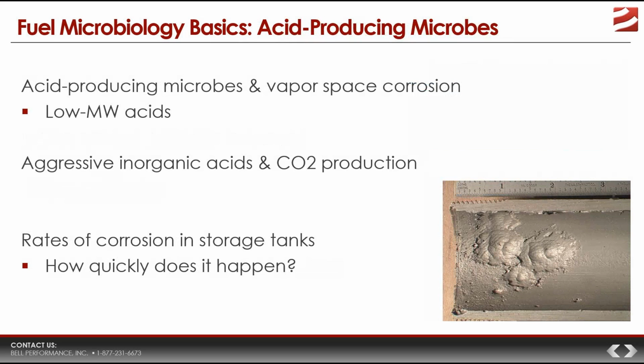Now, acid-producing bacteria typically produce short-chain fatty acids and low molecular weight acids, things like acetic acid, formic acid, and lactic acid. What these bacteria will do, and this is where we start talking about vapor space corrosion, is actually use the hydrocarbon vapors as fuel, and then create colonies in the tank overheads, where you not only have these fuel vapors, you also have water condensation. And so you can have the formation of biomass that almost hangs down like stalactites. ASTM D6469, the standard guide for microbial contamination in fuels, actually references that phenomenon. So that can happen.